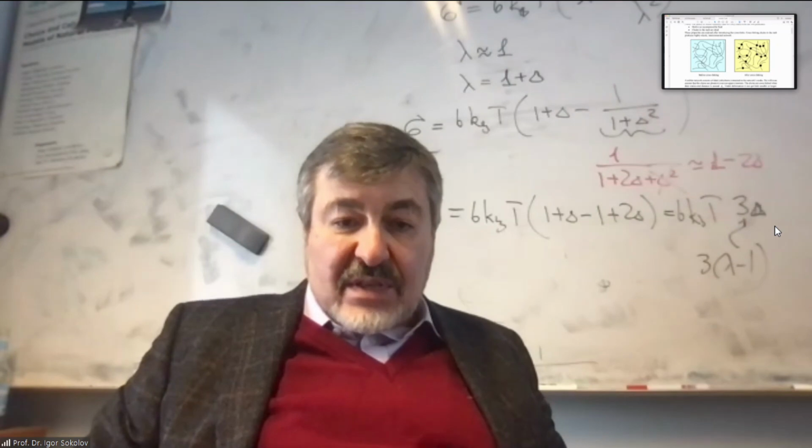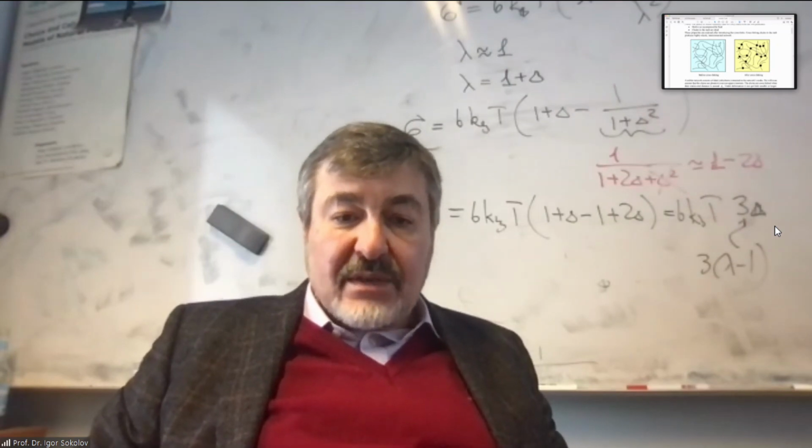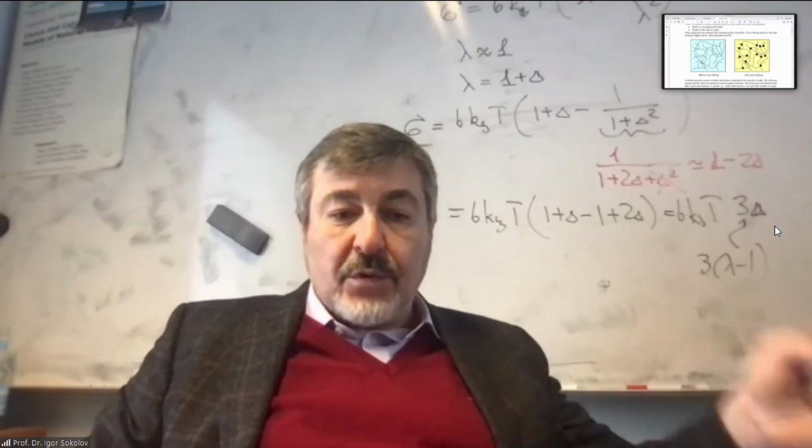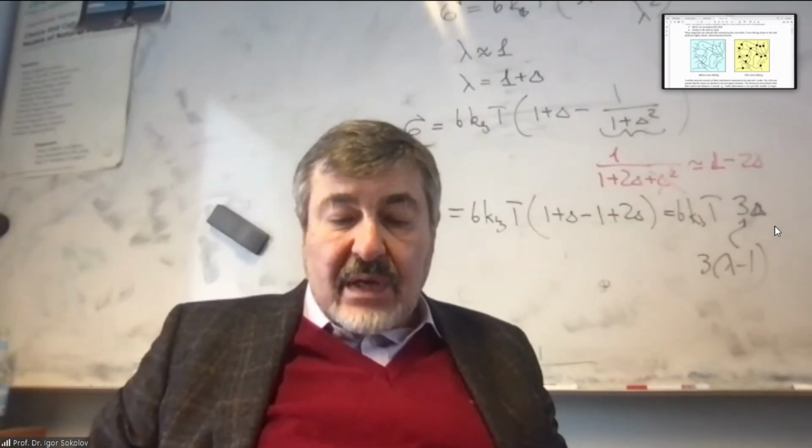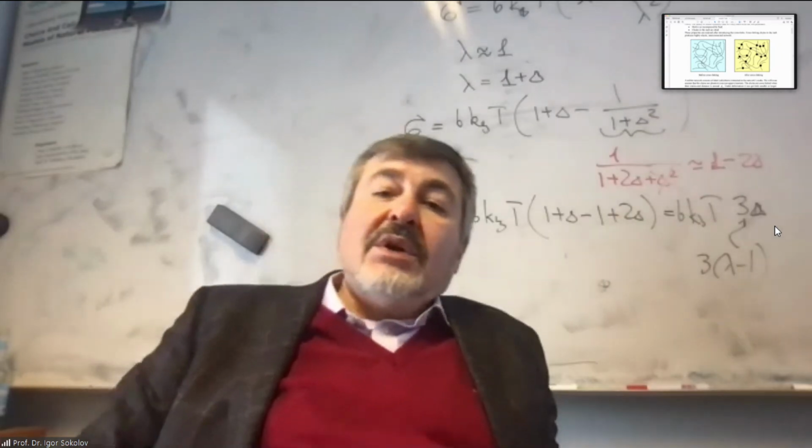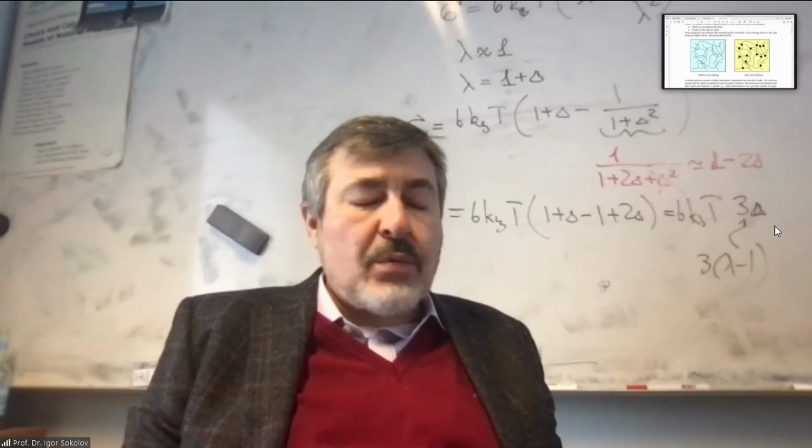You have a transition, it's a phase transition. It happens at some concentration of cross-linkers. You have a transition between fluid and solid. And this is what I wanted to talk about tomorrow in a very simple setting. Because I will only show some parts of the corresponding mathematical theory without even going into detail for polymeric systems, because they are not quite well investigated.